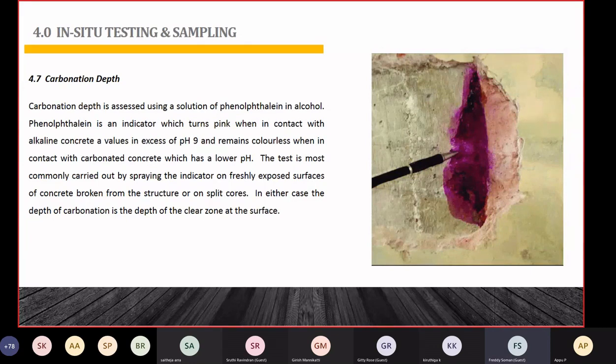This is how we determine the carbonation depth. We make a fresh surface on the concrete, and on that fresh surface we spray a phenolphthalein indicator. When the indicator turns pink, it means the concrete is not carbonated. Sometimes when we spray phenolphthalein onto the fresh surface, if it shows colorless, that indicates that it is carbonated. Carbonated means pH would be less than 9.